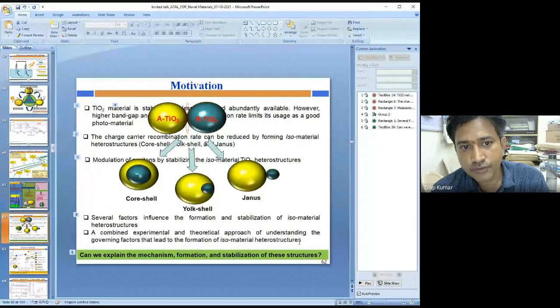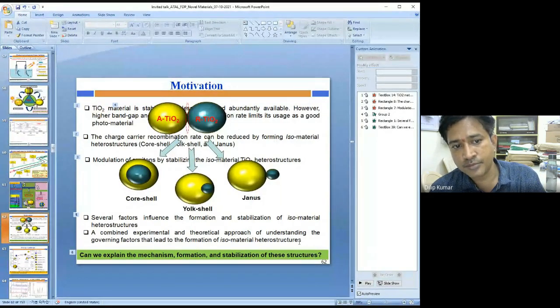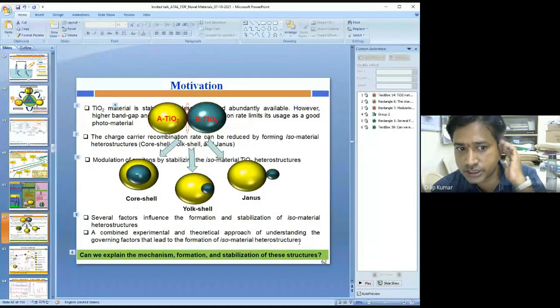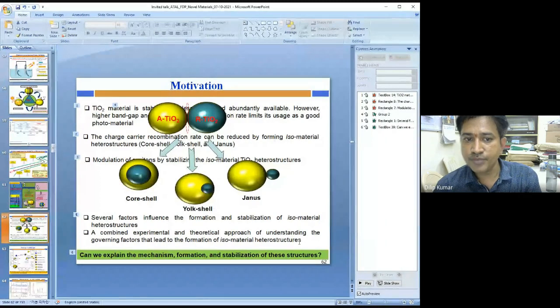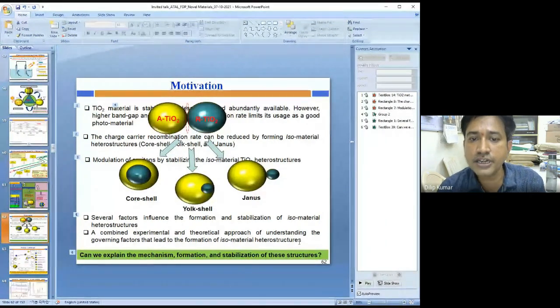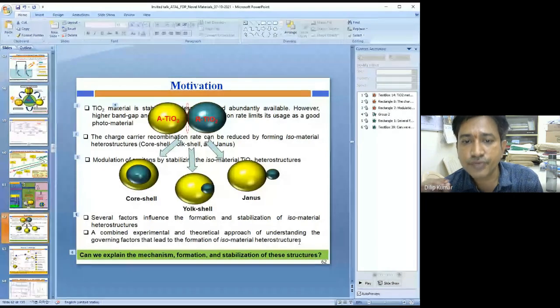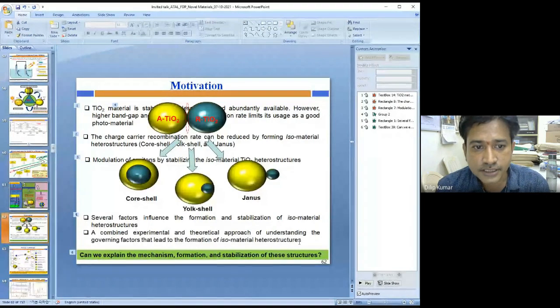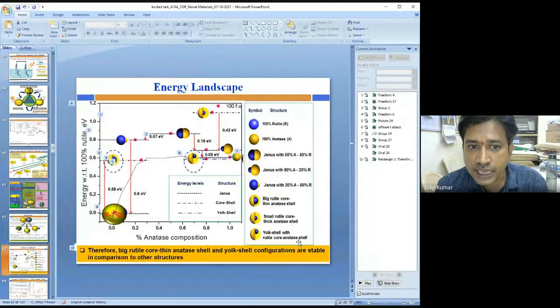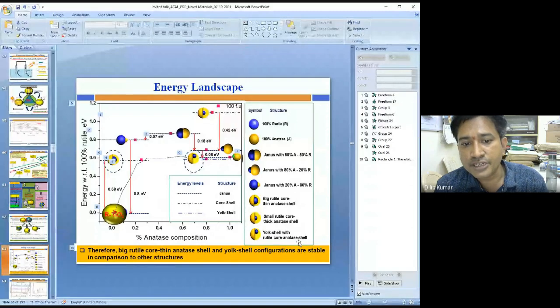So I considered the two main important phases of TiO2, which we call anatase and rutile. Then I understood there are new forms of these anatase and rutile, as I showed in the slide: core shell structures or yolk shell structures or Janus structures. The intention of making these structures is that we can modulate the electron hole pairs, which is very important in improving the PEC efficiency. So I started synthesizing these and understood the energy landscape with some computational calculations.